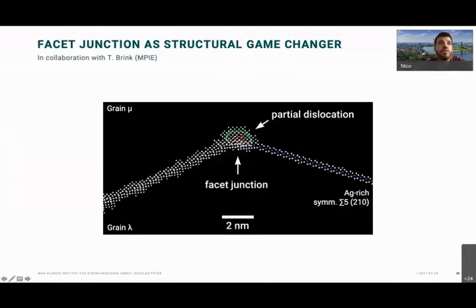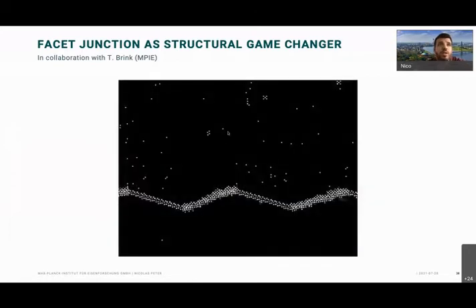And then to confirm or to prove to you that this is happening, we also performed a closer look in MD simulations. And here you see that partial dislocation is coming out of the facet junction. So apparently the facet junction is the point that is of importance here and makes the nucleation point. So hopefully you will see the video now playing.